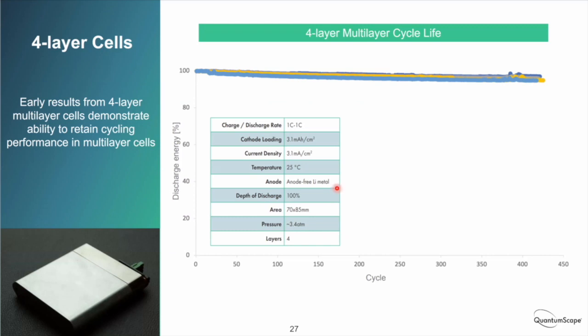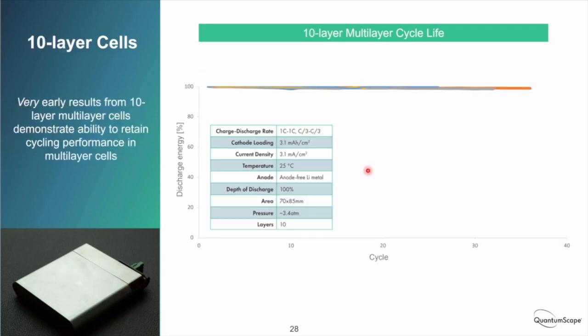The goal we had for ourselves was to prove that four layers could work and then go up to 10 layers by the end of the year. So we don't have the full 10 layer demonstrations yet, but just the very earliest 10 layer cells that we've put on test show that 10 layer cells can work.